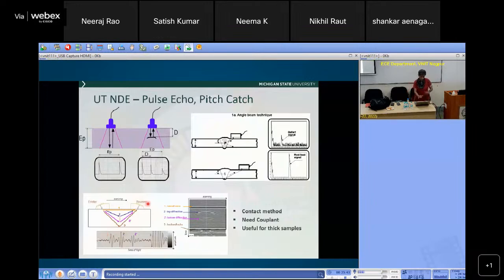So for weld inspection, if you look at submarines, for example, the submarines are made of 2-inch thick steel, and you cannot build entire submarines of one material, right? They take 2 feet by 2 feet sections and weld them together. So there are miles of welding that need to be inspected. Cracks develop in the heat affected zone of the welding. So a lot of weld has to be inspected. So we typically use a pitch catch method. What we show here though is a pulse echo. The same transducer goes in, and some things get reflected depending on the angle of your cracks, and you get